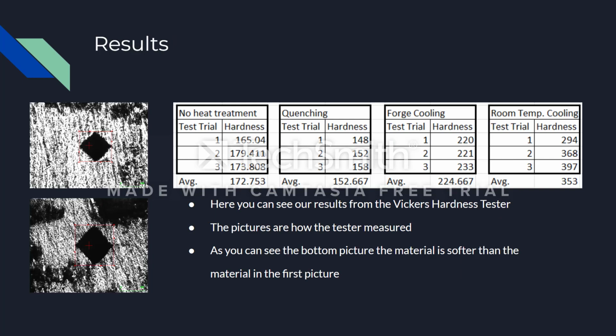Here are the results. You can see the average of all three cooling processes and the no heat treatment control metal. You can also see the diamond indentations from the Vickers hardness tester, with the top picture being a harder metal which has a small diamond shape, and the bottom picture being a softer metal which has a bigger diamond shape.